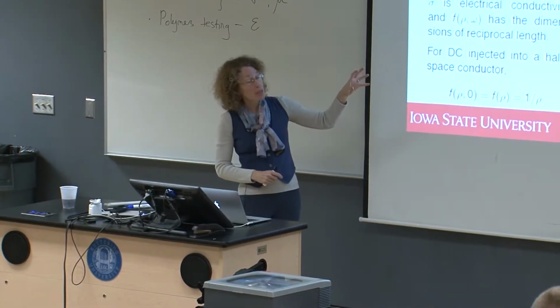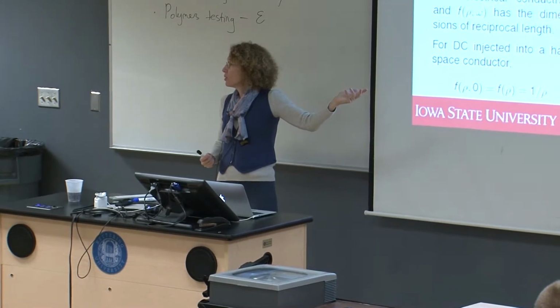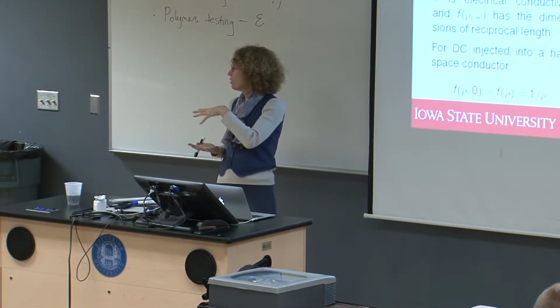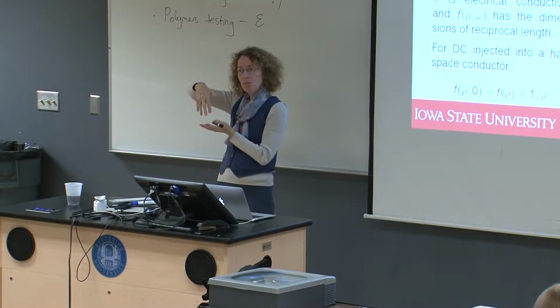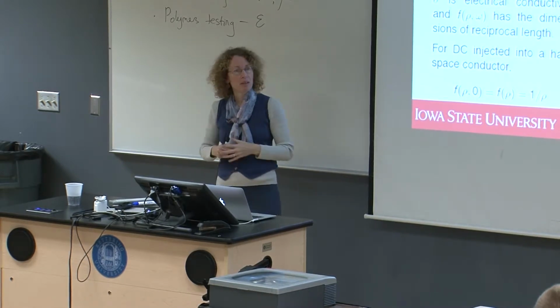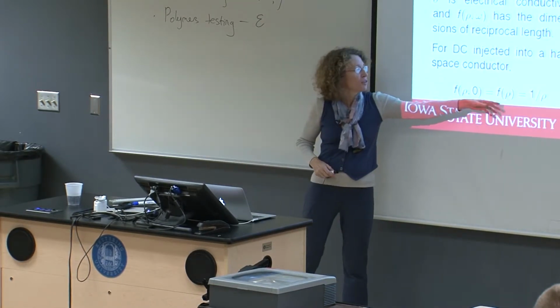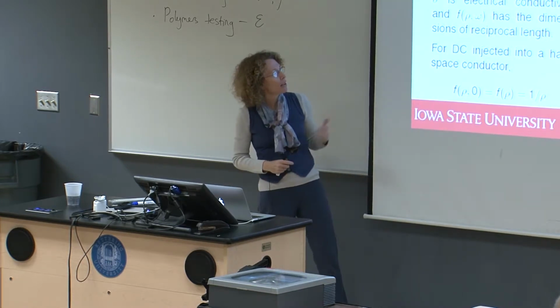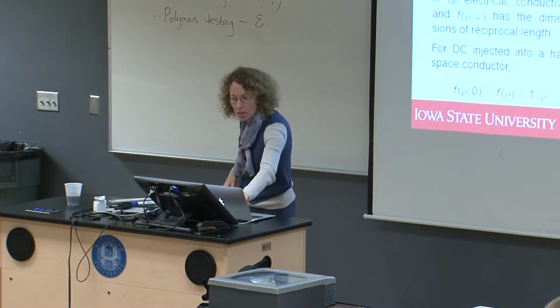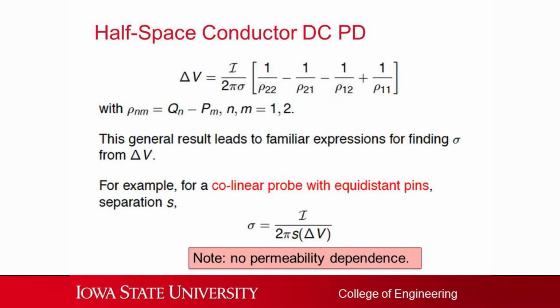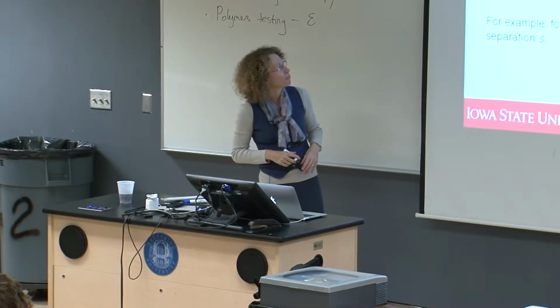Now, in some cases, practically, that will actually be a good formula, because if you have a particularly thick material, and if your probe pins are quite close together, then actually this formula will be valid, and it's a very simple calculation to determine potential drop. And that's what that would look like. You have potential drop equal to the current divided by something, 2 pi sigma, and you have those distances between the different 4 points of the probe.